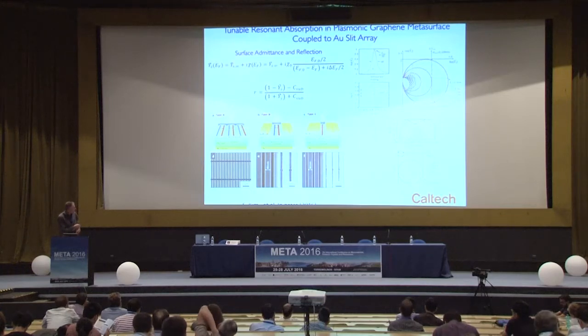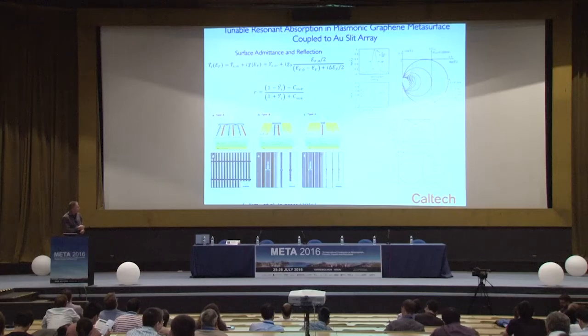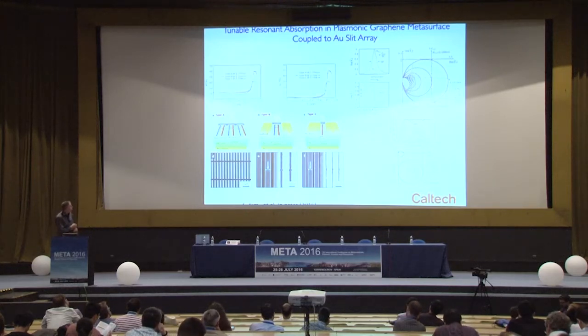And what we found actually was that this kind of structure, where we couple graphene nanoresonator ribbons to the slit arrays, allows for a much better ability to match the impedance of the graphene for the mobilities of graphene that are accessible in these kinds of experiments. The mobilities are rather low, in the few hundred centimeters squared per volt second range, as you go through all of the processing required to make resonant structures. And so indeed what we saw was that this allows one to raise the absorbance of a single monolayer of graphene as high as 70%. So we're getting very close to unity absorption.